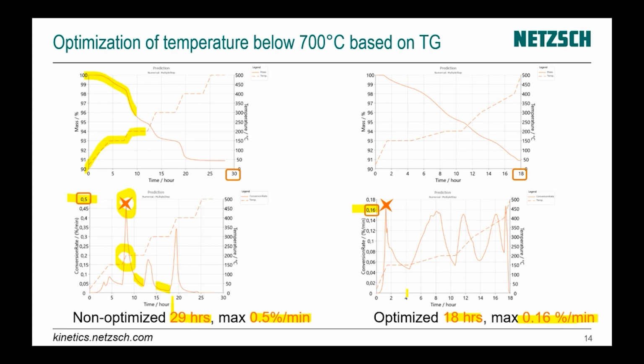So we have decreased the decomposition rate, we have improved the quality, and we have reduced the time during our sintering process. So this is the optimization of debinding below 700 degrees C. And now here we have an optimized temperature profile, something like this, and a more or less constant decomposition rate. Here is our result.